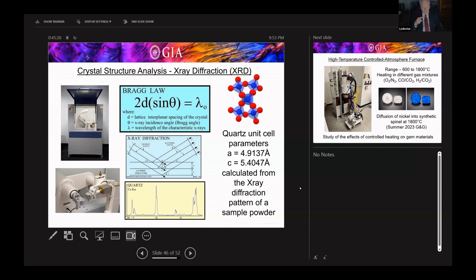So the equation there at the top, the Bragg equation, you have the incident X-rays, the lambda naught, you have the angle, and you can calculate the sine of the angle, and you can solve this equation for the d, which is the spacing of the atoms in the crystal structure. So if you have a powder, or if you're able to rotate the material around, so you're sampling a lot of different directions in the crystal lattice, you can calculate the unit cell parameters and all the d spacings. And this is the standard way that minerals have been identified. It doesn't tell you about chemistry, it tells you about crystal structure.